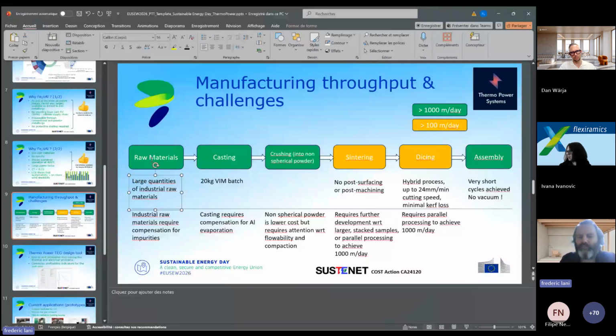Okay. Then if we go to casting, we have revamped a vacuum induction melting oven which allows us to manufacture 20 kilograms of material per batch, which is a very good quantity regarding our throughput objectives. But the point is that casting requires very accurate compensation, for instance, for evaporation of aluminum.